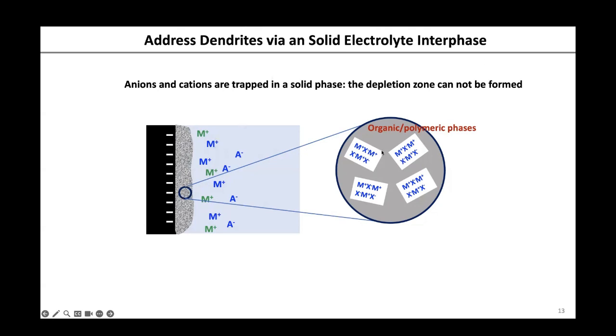And because you have cations and anions in this layer, guess what? It will not generate that vacuum of ions. You won't have the depletion zone anymore. So SEI will be a very effective way to prevent dendrite formation for metal batteries.